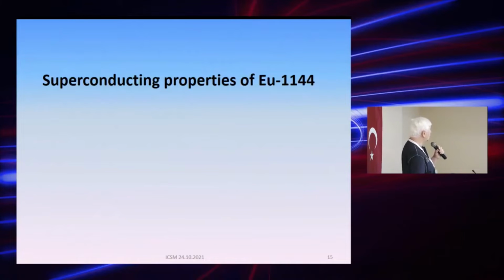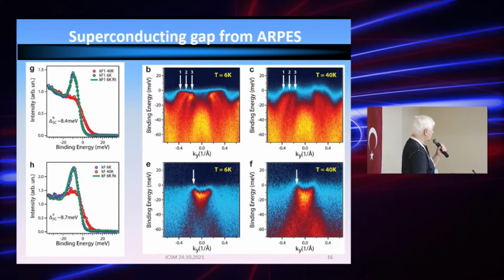Now we shift gears to superconducting properties of this compound. And first of all, as we do ARPES measurements, we can also trace the evolution of the superconducting gap. We can do it because these are momentum selective measurements. We take measurements as a function of energy, tracing different positions of, say, the valence band and electron bands, and we see how the energy states transform as a function of temperature, and the spectral weight transfers to the wings, clearly showing development of the superconducting gap.